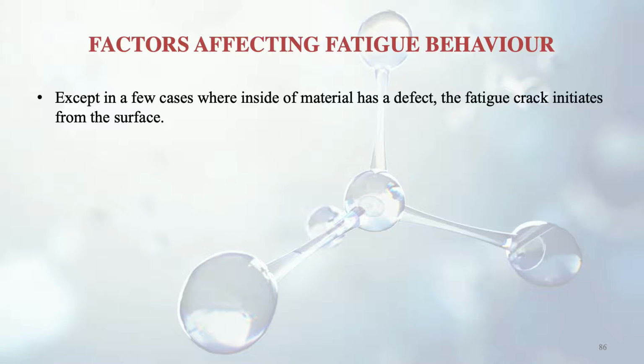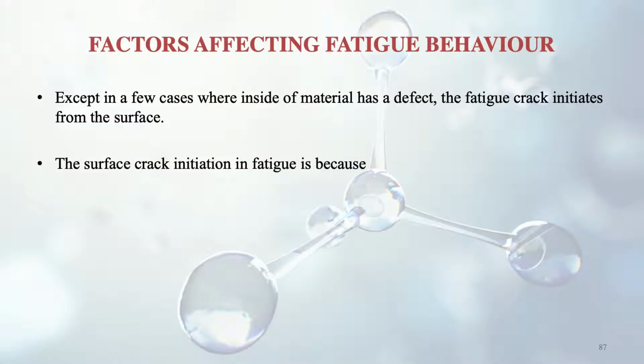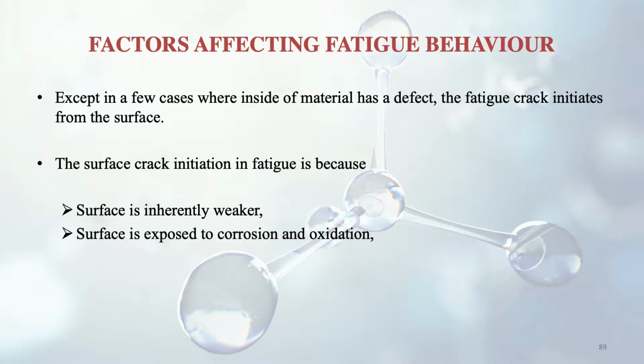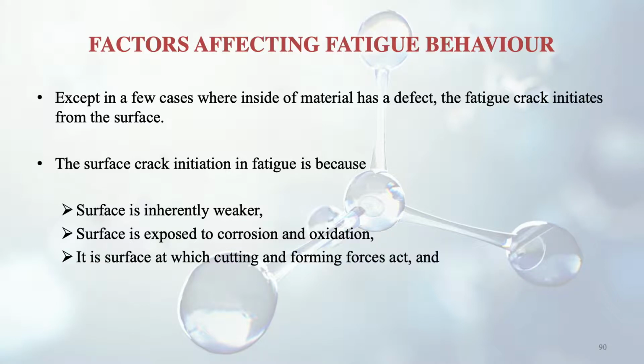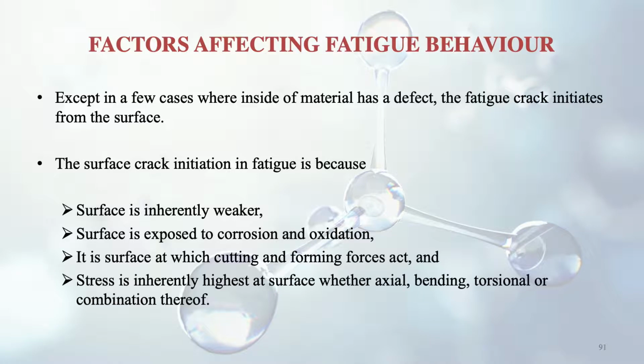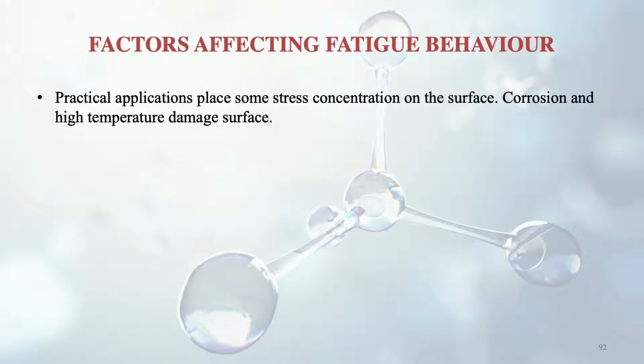So on this gradual scale we are going towards more finished specimens. Except in a few cases where the inside of the material has a defect, the fatigue crack initiates from the surface. So it is mostly a surface phenomenon. Only exceptions are there where the crack may start from inside of the material. The surface crack initiation in fatigue is because the surface is inherently weaker, the surface is exposed to corrosion and oxidation, it is at the surface that cutting and forming forces act, and stress is inherently highest at the surface, whether axial, bending, torsional or a combination, whatever it is. So we see here that it depends on the surface how the fatigue failure will take place or how the crack will propagate. Practical applications place some stress concentration on the surface.